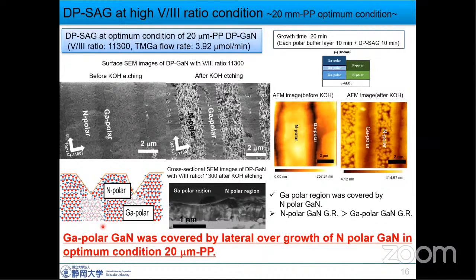This result indicates that the nitrogen polar gallium nitride growth rate is faster than the gallium polar gallium nitride growth rate. This result indicates that the optimal growth condition in the 20 micrometer pitch pattern is different from the 4 micrometer pitch pattern one.